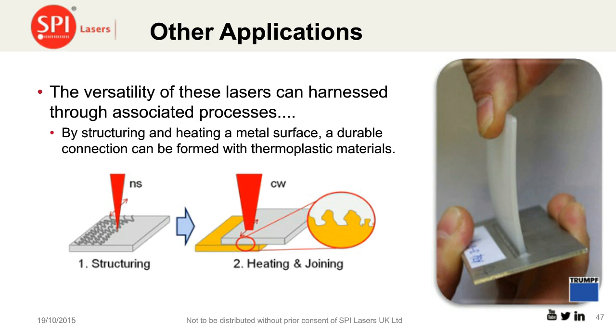Let's not forget that these lasers are capable of doing other things. And this is an interesting application that my colleagues at Trumpf developed, where they're structuring metal and then bonding plastic onto it. So you're using the ablative and engraving capabilities of the nanosecond pulses. And then you can put a piece of thermoplastic on there, turn it onto CW, pass over that, remelt it, it will flow into the grooves, and again you get a strong joint.